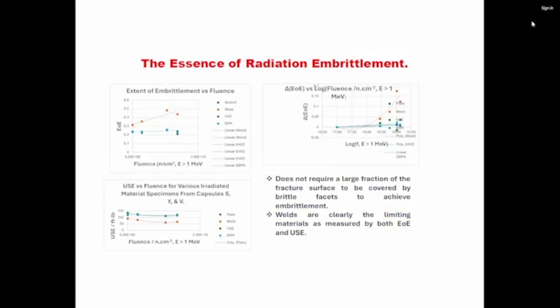Okay, here's the extent of embrittlement versus fluence. And I've left the error bars off on this because I wanted to illustrate one point which seems to be consistent. You'll see that the weld metal is by far the component that is most sensitive to fluence. But you'll notice that for the upper 2 points on the weld metal, it appears that the extent of embrittlement goes to a maximum.